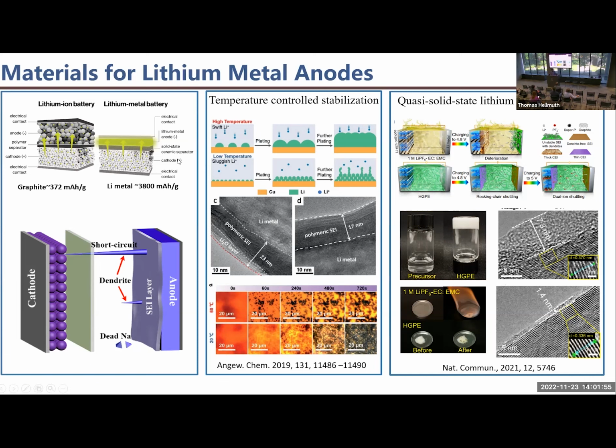So for example, if you see this figure, this battery is tested at 20 degrees centigrade. So there's a lot of dendrite formation. This battery is tested at 60 degrees centigrade. So it is more homogeneous after 720 seconds. There are other characterizations as well, but this is the only space I have at the moment.